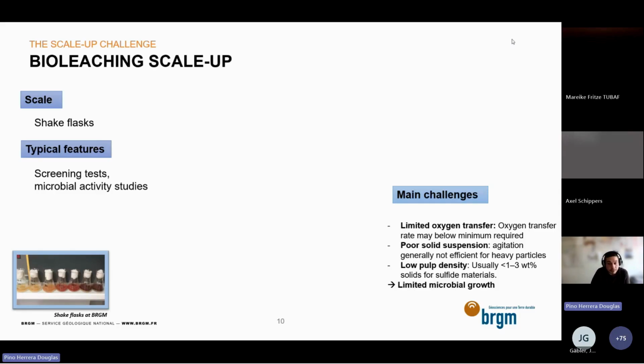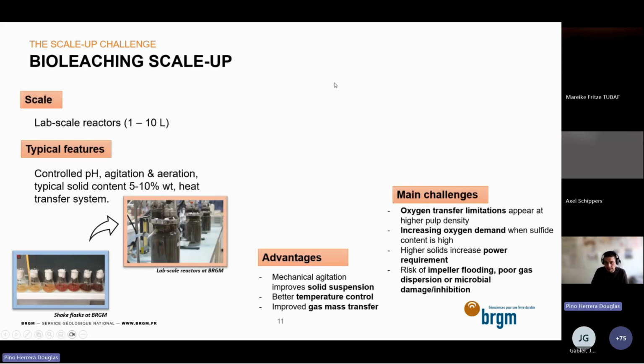There is poor solid suspension because the agitation is generally not very efficient, particularly for heavy particles such as sulfide. That's why we always choose low pulp densities, usually 1 to 3% by weight of solids in the system. This may have an impact on microbial growth. We know that bacteria may grow on it, but these are not the ideal conditions. But that's fine because then we can go to the lab scale reactors.